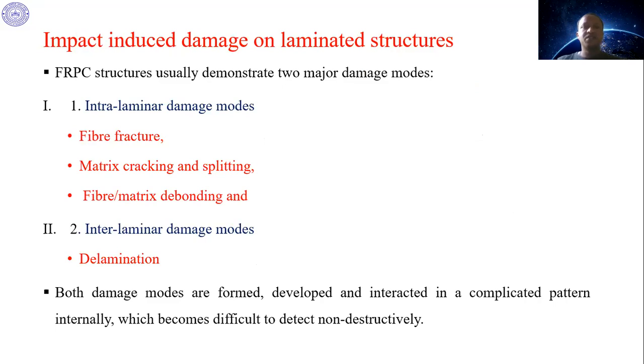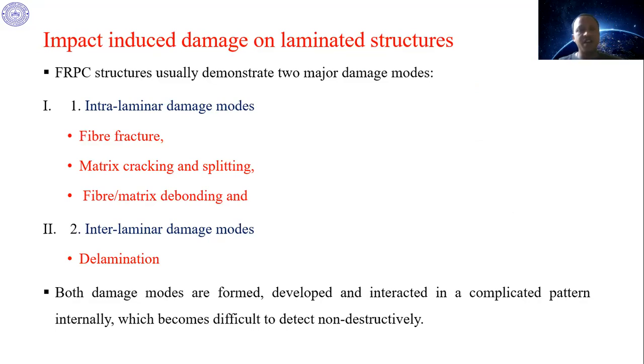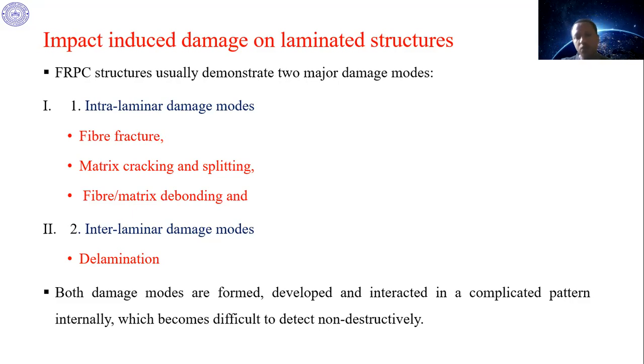Impact-induced damage includes fiber fractures, matrix cracking, and fiber-matrix debonding, which are classified as intralaminar damage modes. Another mode is delamination, or separation of adjacent layers, which is the interlaminar damage mode. These two damage modes develop and interact in complicated patterns internally, making them difficult to detect non-destructively.